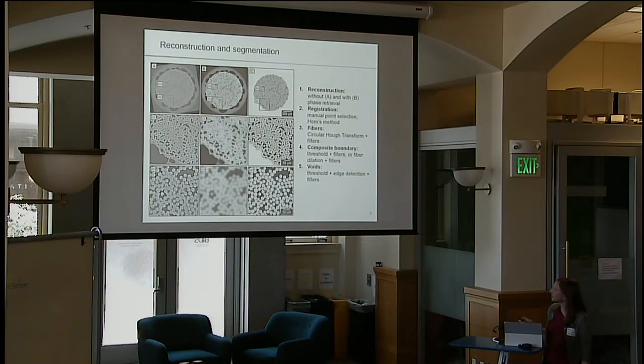And then finally, to segment the voids, we use the reconstruction with phase retrieval, where the difference between the voids and the matrix is a lot more clear. The voids are the black regions, and the matrix is the lighter gray regions.